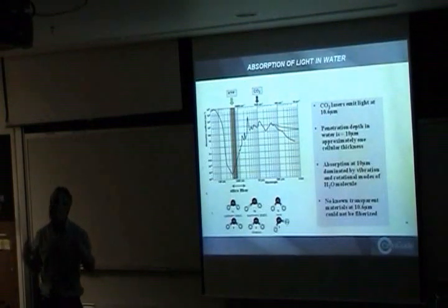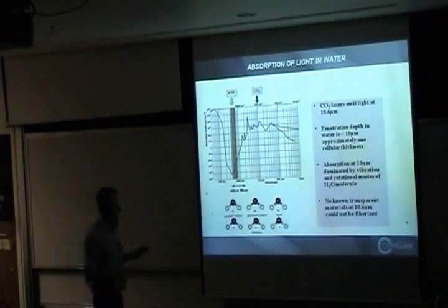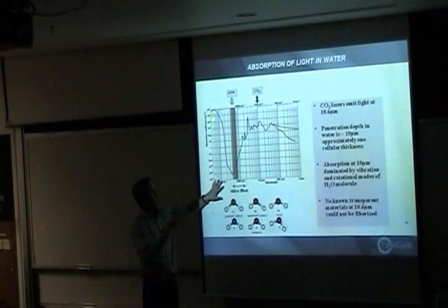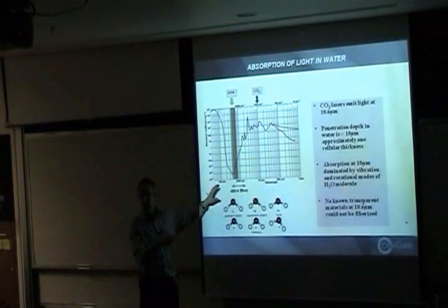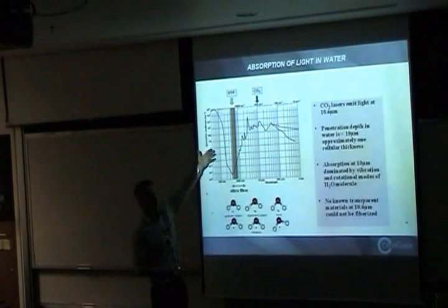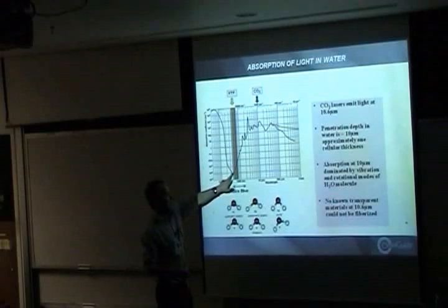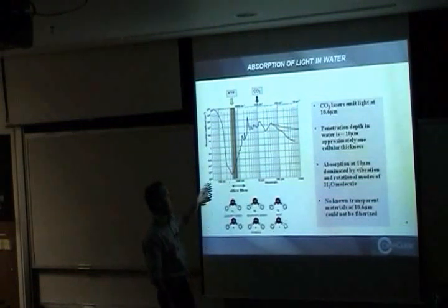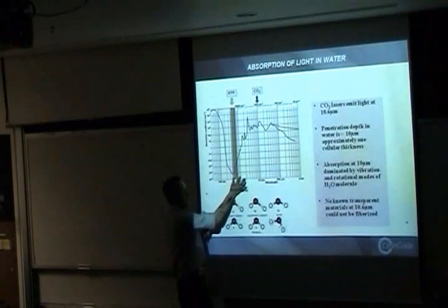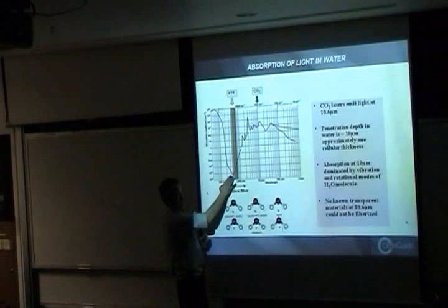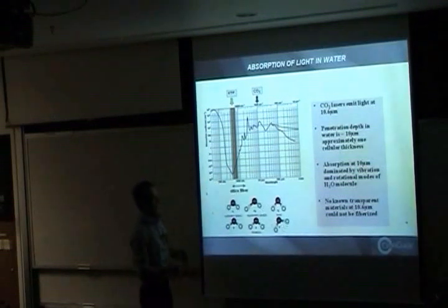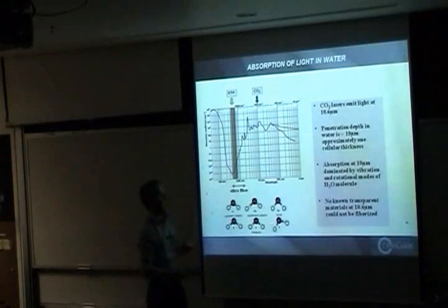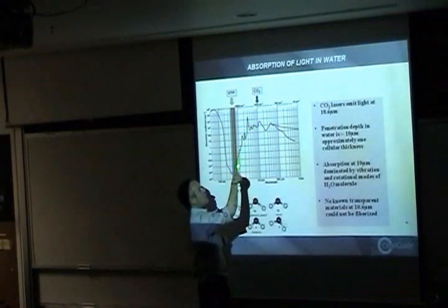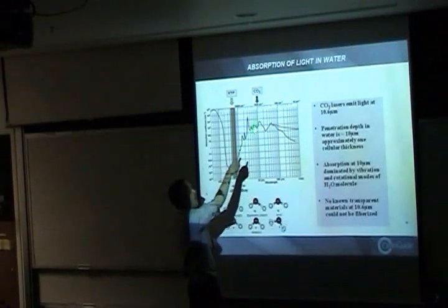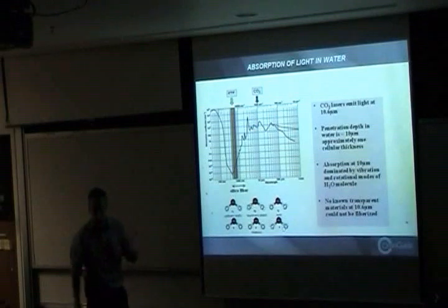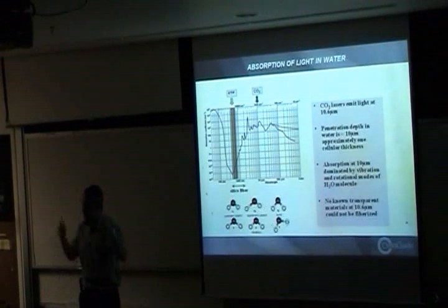Let's talk about what good these fibers can do in the world. This plot shows the absorption coefficient in inverse centimeters of electromagnetic radiation in water. And what you can see here, on a log scale, is that the absorption coefficient for radiation below 1 micron is very, very low. In fact, green light at 532 could penetrate through significant lengths of water. And as you go into the infrared, this absorption coefficient climbs by many orders of magnitude. And around the CO2 wavelength, the penetration depth turns out to be on the order of 1 wavelength in microns. Why is that interesting?